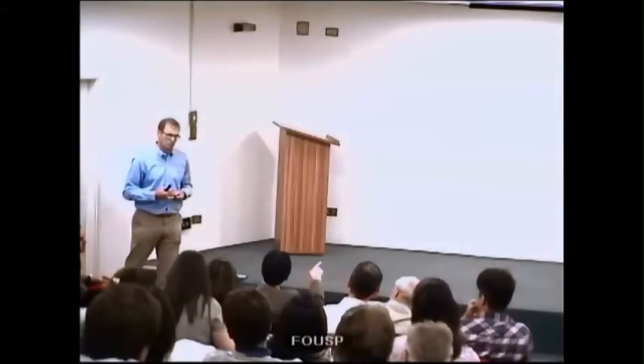I have a question following Jason's question, on fast fracture versus fatigue fracture surface. If you bring up the PowerPoint slide, I see the specimen preparations are very different in these two cases you showed. For fast fracture, you have beveled surfaces, chamfered corners, but the fatigue specimens have sharp corners. And it looks to me like it's initiated from the corner. You're right. This is a mistake I made because I selected pictures for this presentation which clearly show what I would like to point out.